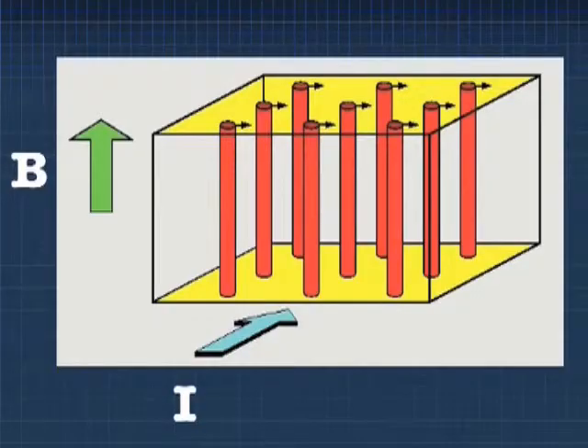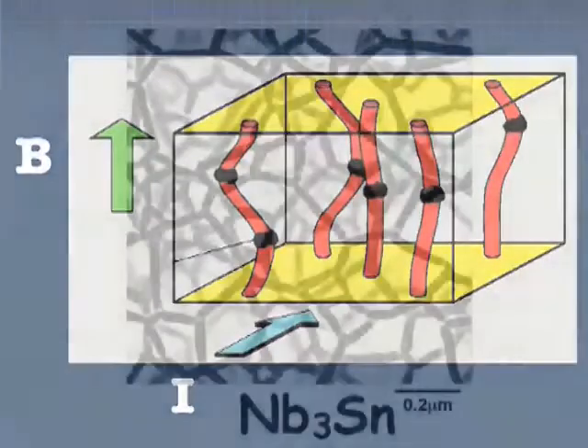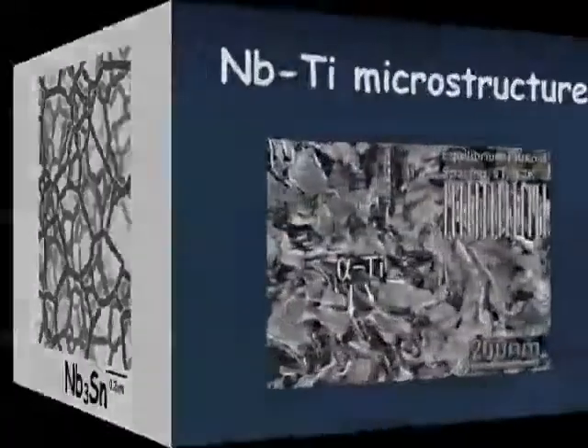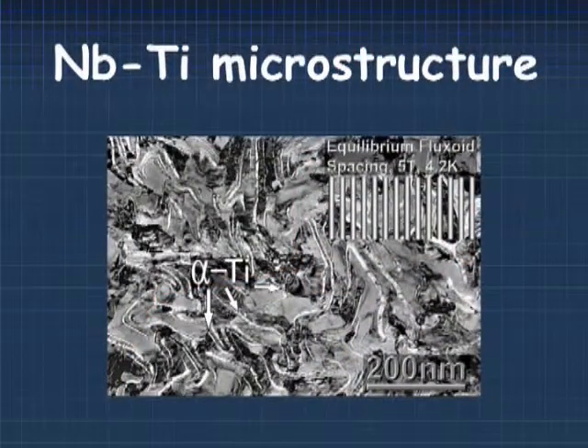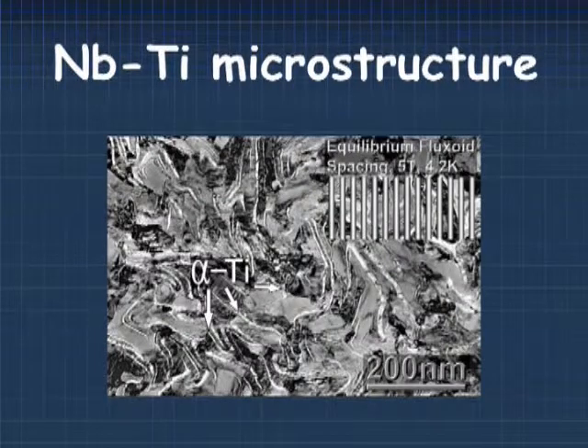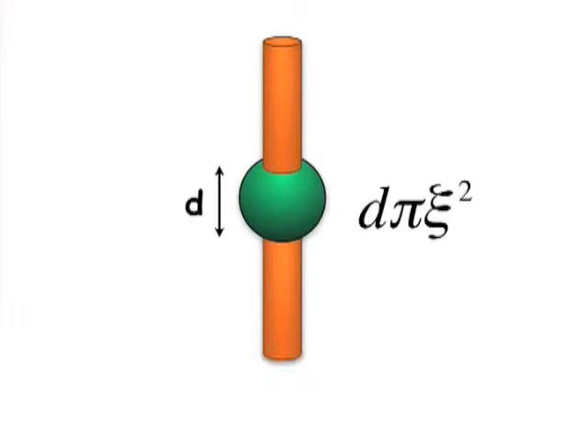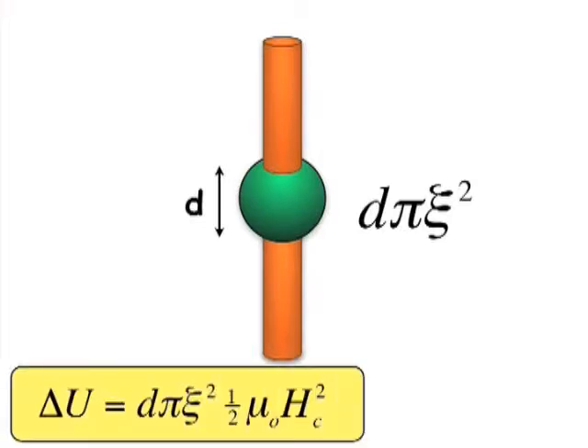The way in fact you get the best properties out of something like niobium-titanium or niobium-3-tin is to stuff the material full of defects. In the case of niobium-titanium, we have these little second phase particles of not superconducting, that's to say normal titanium, and we just make these one or two nanometers thick. And so we have this extremely dense array of these real nanoparticles, 20-25 volume percent not superconducting, sitting in a continuous superconducting matrix, and all of these interfaces have a wonderful effect on the way that flux, which is quantized in the superconducting state, and most of all, very important, is they can be pinned.